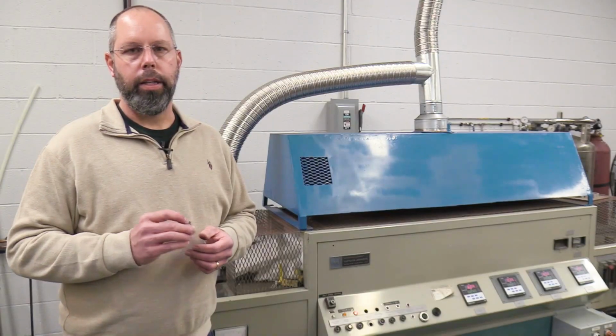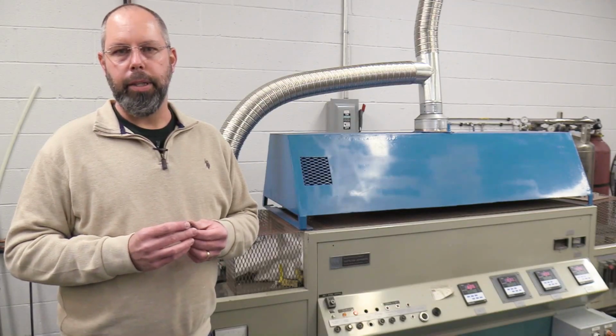Now, there's lubricant that's been added to the powder that allows for the compact to be ejected from the die, and to bind the particles together. It is transported to sintering. This part is considered a green part at this time and has little structural strength, and if dropped, it will break. To gain structural strength, the part needs to be sintered.